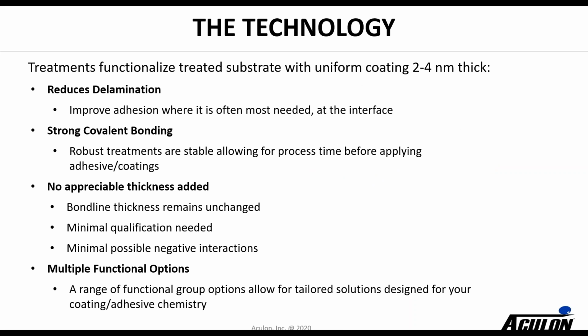So the technology is a nanoscale technology. Most of our primers are typically going down in a thickness of 2 to 4 nanometers. And for adhesion, the main thing is to reduce any sort of failure at that interface, and to prevent delamination, we're doing this by bonding. So we want the chemistry to react strongly to form covalent bonds and really be a stable bond between the substrate and the adhesive or paint.